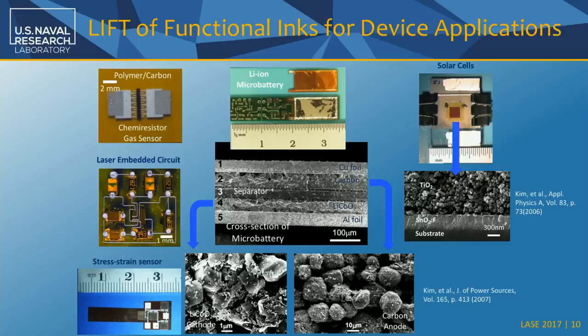And in this case, these are both the anode, the carbon, and the lithium cobalt oxide cathode, to make a stack structure for a lithium ion battery. So these are the kinds of things that we can print. And also polymers; this is a polymer loaded with carbon. Effectively, it's a chemiresistor: in the presence of an organic vapor, it swells and the resistance changes.